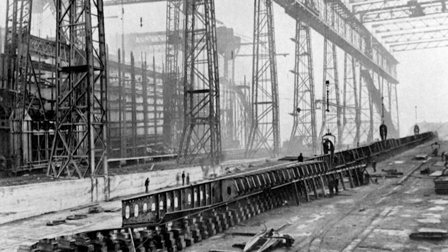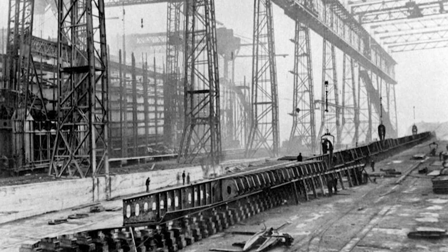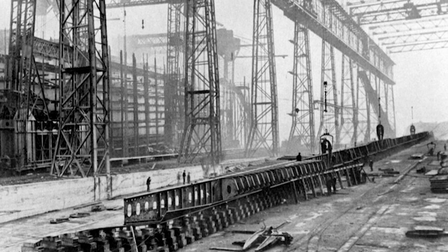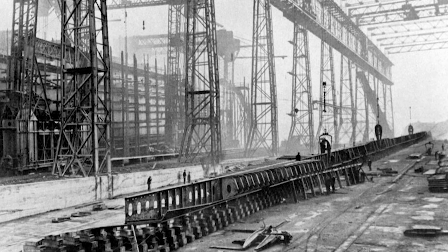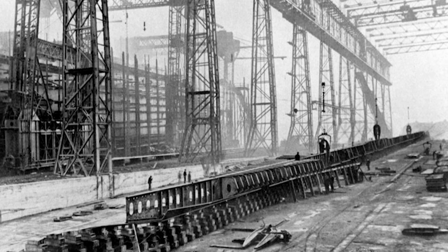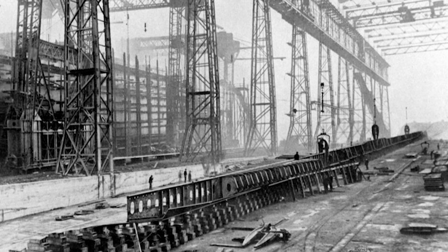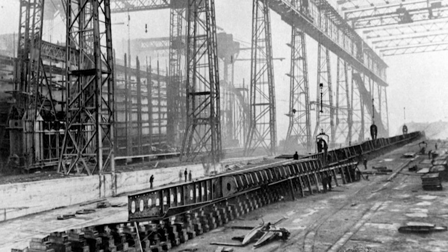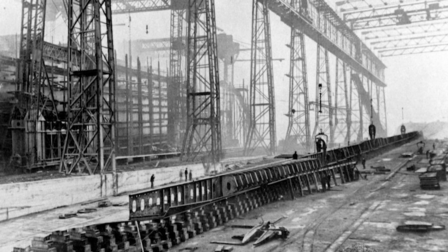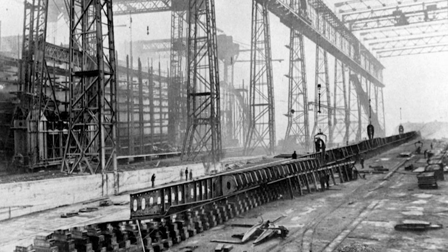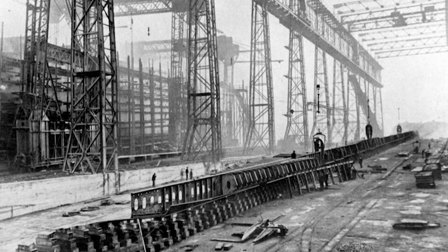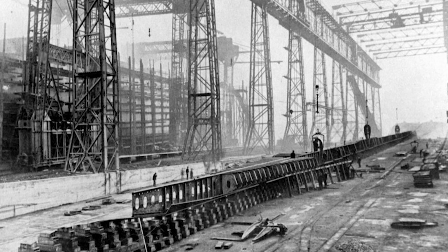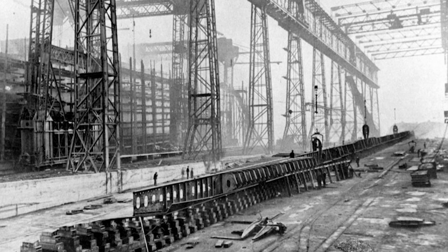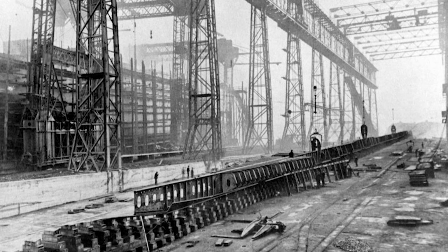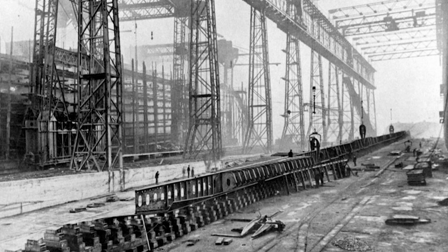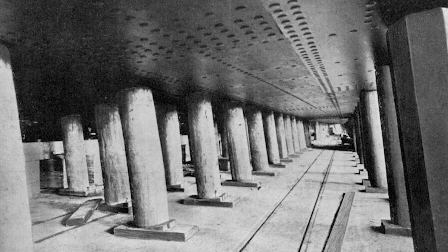immune to catastrophic failure. Riveted ships consisted of thousands of individual steel plates connected by mechanical fasteners, creating natural crack arresters that prevented fractures from propagating beyond single structural elements. Even if one plate became brittle and cracked, the riveted joints would absorb the fracture energy and prevent failure from spreading to adjacent sections. The overlapping construction that traditional engineers had developed through empirical experience inadvertently created the perfect defense